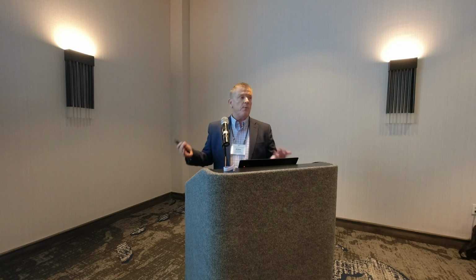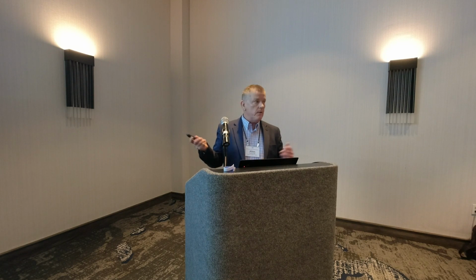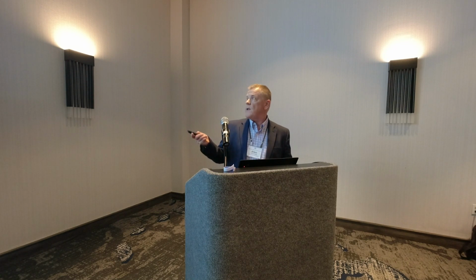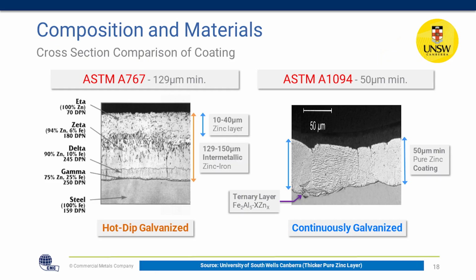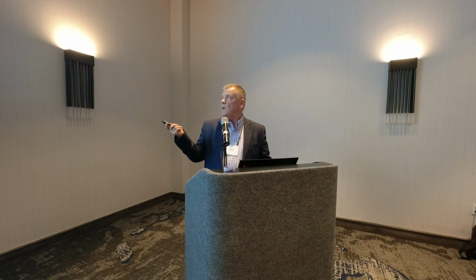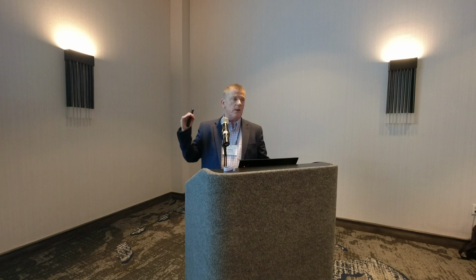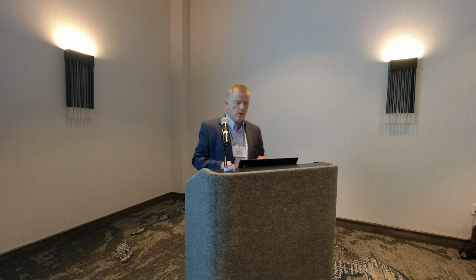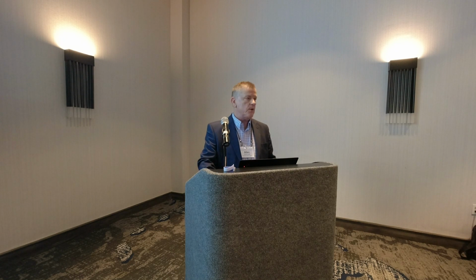So it's an unpredictable situation, what's going to happen whenever it's being fabricated, or if you have an area that peels. And there's a repair method for that if it does occur. But this technology was innovated to address that situation. So what you have in this case is a 50 micron minimum coating. It averages about 65, but it's a pure zinc layer. And so you have a consistent ductility, and so that's what enables it, I mentioned a little earlier, to be fabricated after it's been coated.